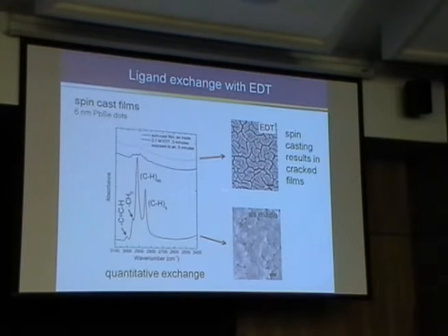And so the obvious thing to do is just to spin coat again, and again, and again, and fill in those cracks and then re-exchange each layer. So sometimes for solar cells that are made by spin coating, you do about 10 layers thick, something like that.